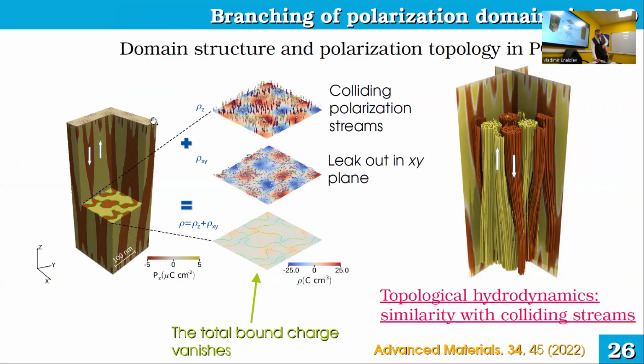Actually, we can see that, results of modeling versus the experiment, the overall structure of domains looks the same. And what is interesting, bound charge near the domain walls is indeed very small. But how to explain it? It can be explained actually in one way. If you have some rho-z component of charge, the charge that comes from head-to-head or tail-to-tail configurations of polarization, it can be compensated by lateral components. So some polarization should be in the xy plane. And then the total bound charge, which constitutes rho-z and rho-xy, is indeed small.